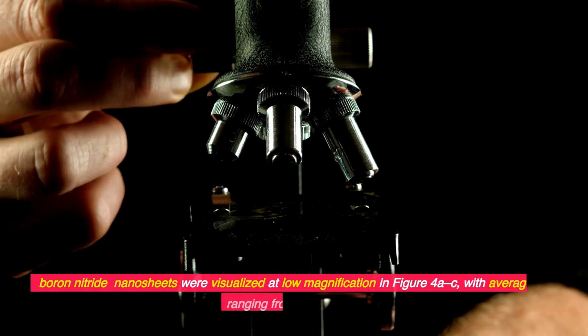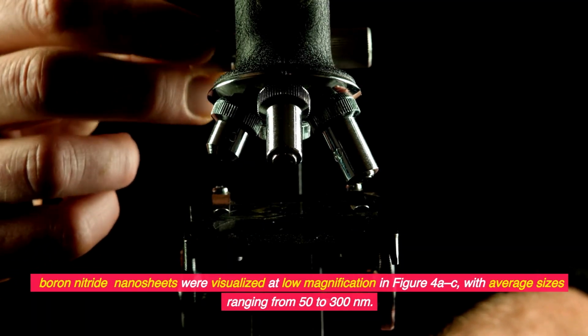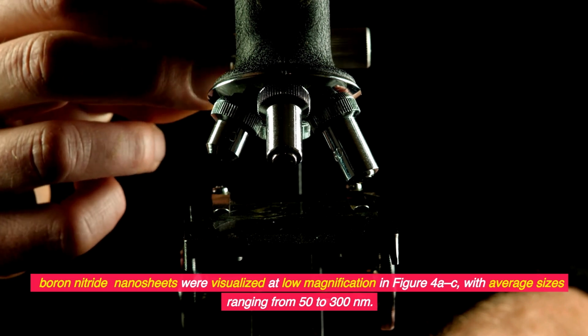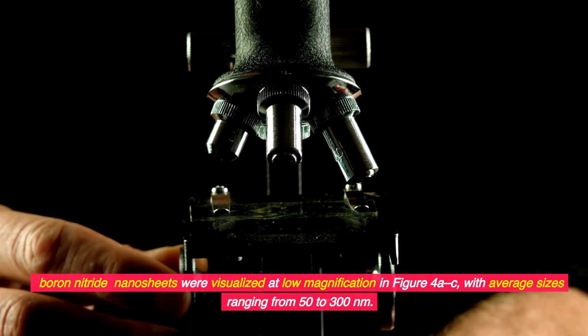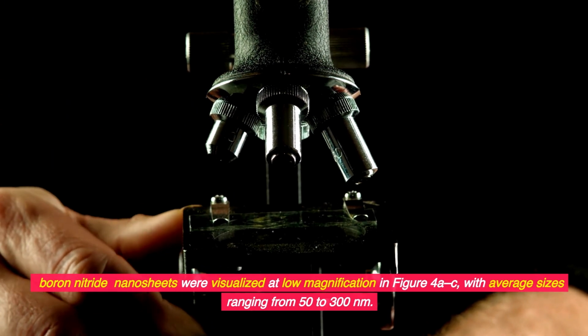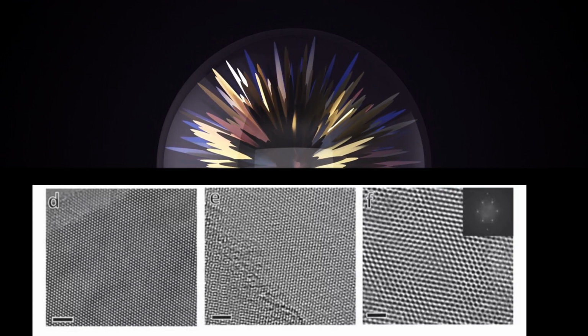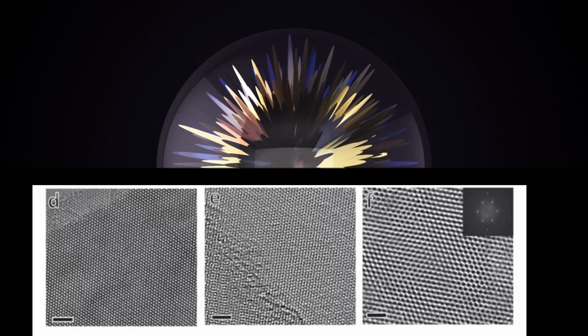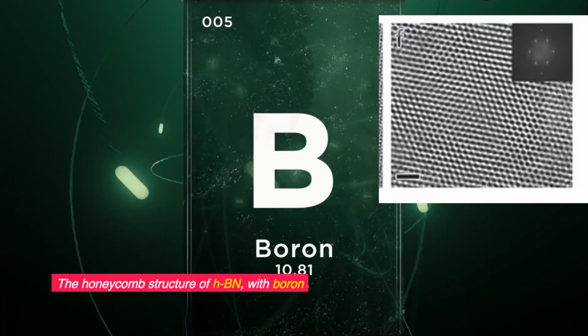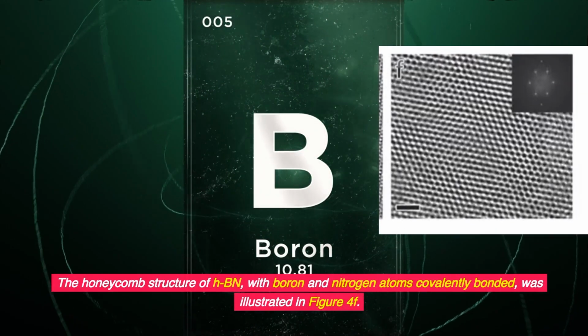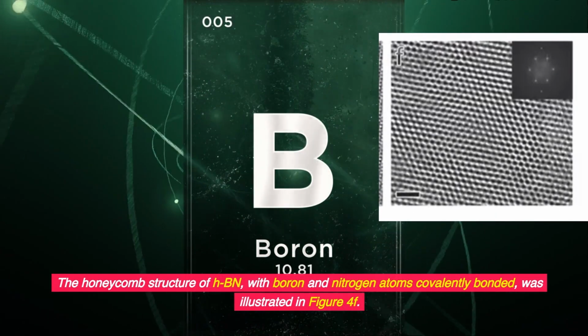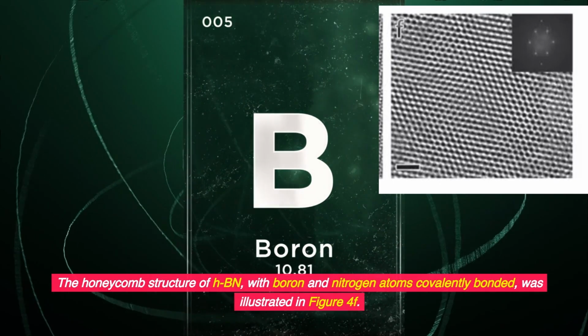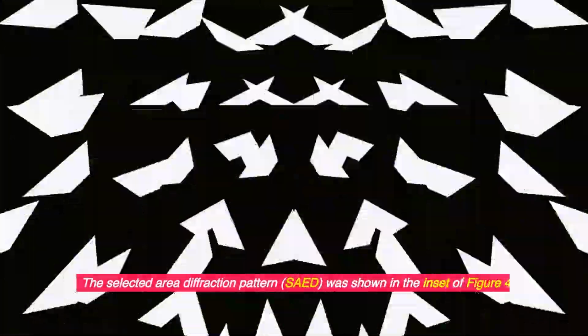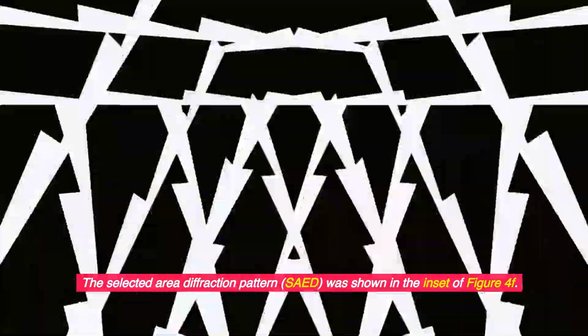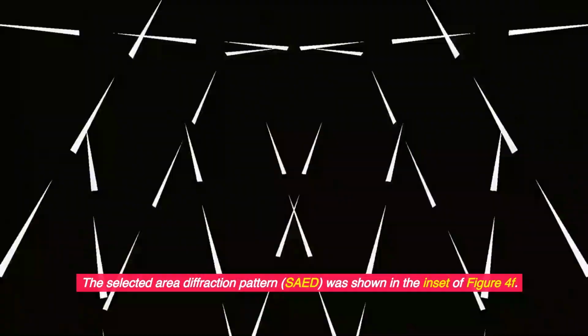Boron nitride nanosheets were visualized at low magnification in Figure 4A-C, with average sizes ranging from 50 to 300 nm. Figure 4D presented the typical atomic structure of BN nanosheets. The honeycomb structure of HBN with boron and nitrogen atoms covalently bonded was illustrated in Figure 4F. The selected area diffraction pattern, SAED, was shown in the inset of Figure 4F.